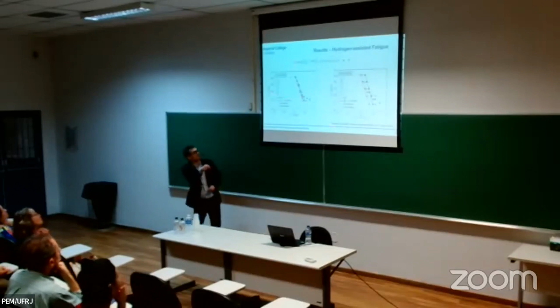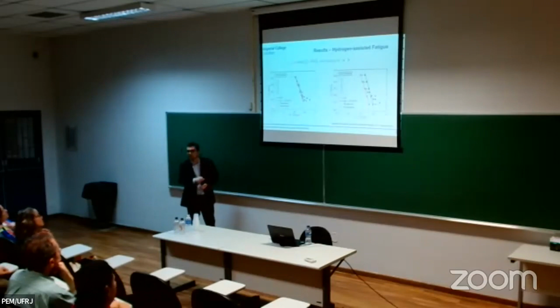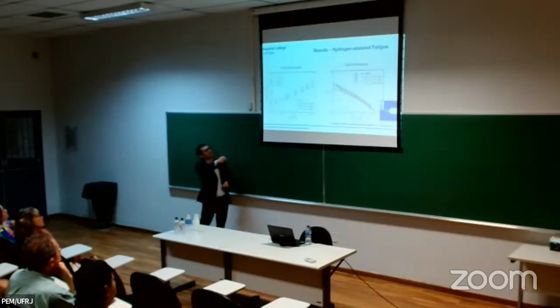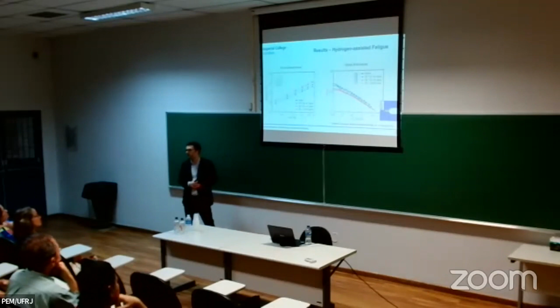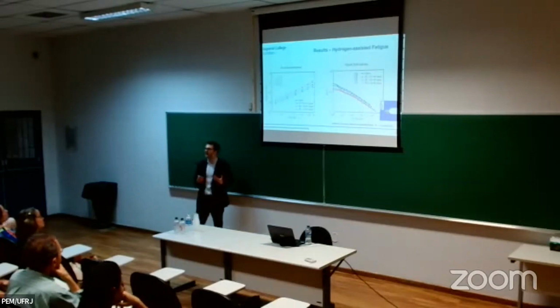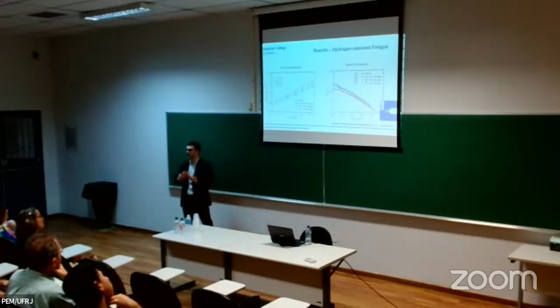And we have recently extended this to fatigue, so you can have a fatigue degradation function, and then you can see here that you can predict virtual S-N curves with and without hydrogen, showing a comparison with experiments. And we can also predict, as an output of the model, Paris law behavior, so we can predict the influence of hydrogen on the Paris law coefficients, and deliver virtual S-N curves for any arbitrary choice of load and environment, as you see here. And these are cycle by cycle calculations, which are computationally heavy, but at the same time very powerful because they allow us to predict fatigue damage for any arbitrary load.